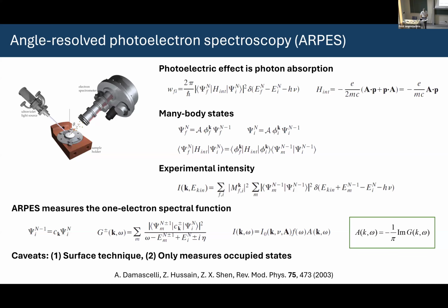Sorry, Peter, can I just ask you, with the development of your reflection yield system, would that be a nice way to do inverse photoemission? No. Why not? Because the electron-hole interaction in most things just dominates. For example, if we measure an insulator, I cannot measure the band gap that way. What you see are the exciton lines, because electrons and holes interact. And even when you don't have bound states, there are excitonic effects that shift spectral weight around. You never really know what the spectral function was on the other side of the Fermi energy.